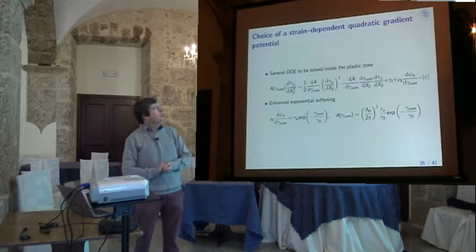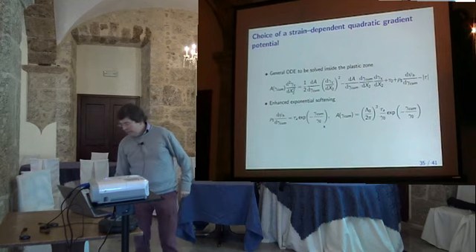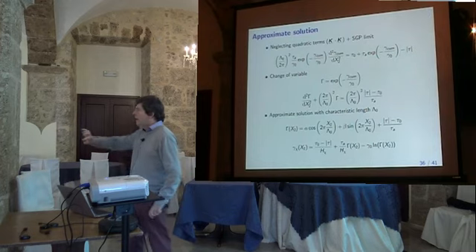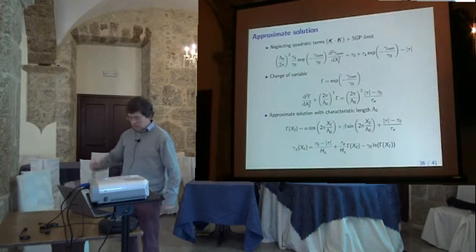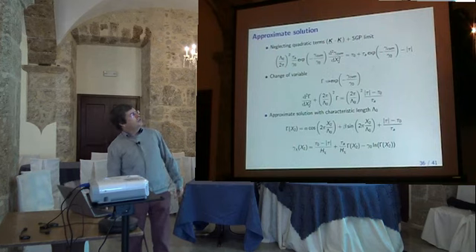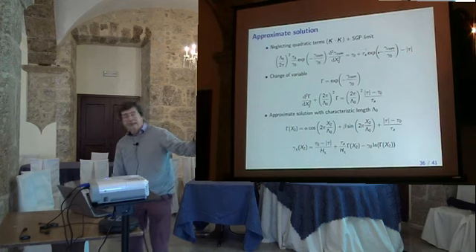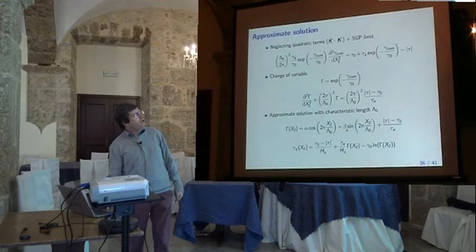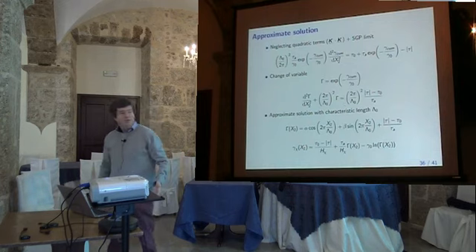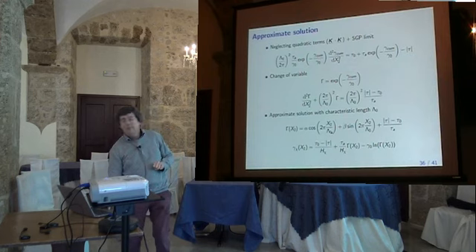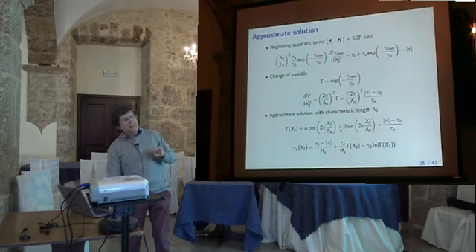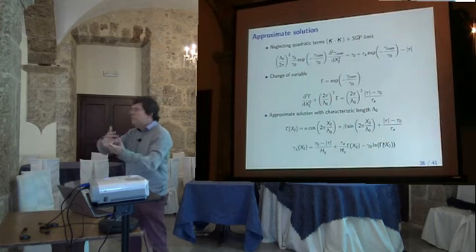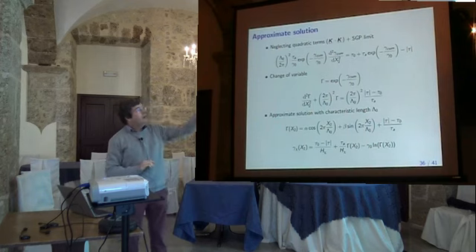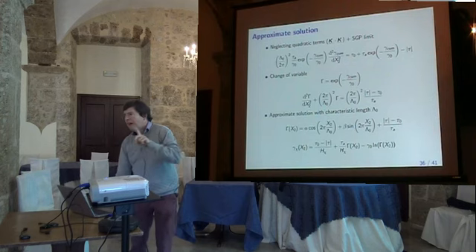And so Jean-Michel has tried to solve this with an exponential function here. He has a nice tentative solution, approximate solution, where in fact we discard the nonlinear term because it's too difficult. And he has found that if you make a sort of change of variable into this differential equation, which now is terrible because you have exponential inside, so this is nasty. So you do this change of variable and you can work out a solution which is like a harmonic solution with a constant width, this capital lambda 0. It's not exactly that, because you see the solution is this harmonic solution and there is a correction due to this gamma term, exponential term, which remains small sometime. I will show it now.